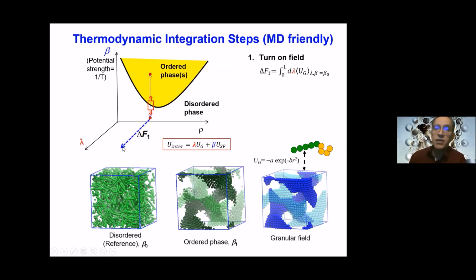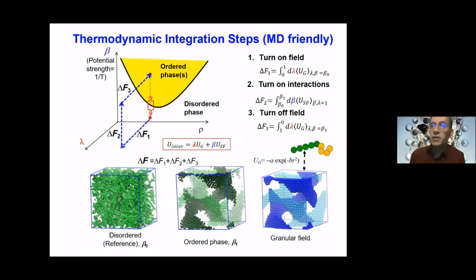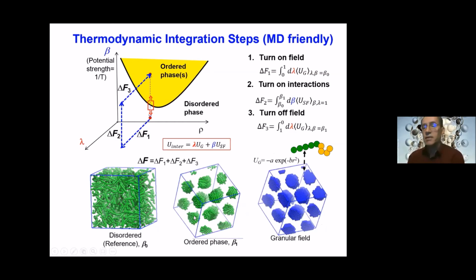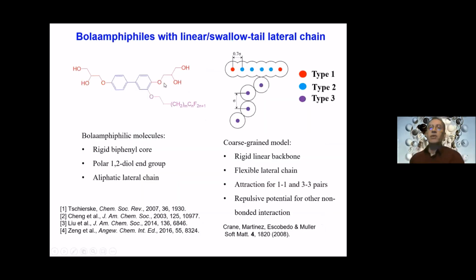But you have to make sure that this change is reversible, or else it wouldn't work. So once you are there, at something that resembles the ordered structure, you can turn on the interactions, say by increasing beta. And finally, of course, you'll have to remove the field gradually. So once you add the three contributions, 1, 2, and 3, you'll have the total free energy difference between this phase and that phase, which is what you want. Now, if there is another candidate ordered phase, let's say the cylindrical phase, then you repeat the same process again, and then you compare the final delta Fs to see which one has the lowest free energy in the ordered state. So that's what we'll do for our bolaamphiphiles.